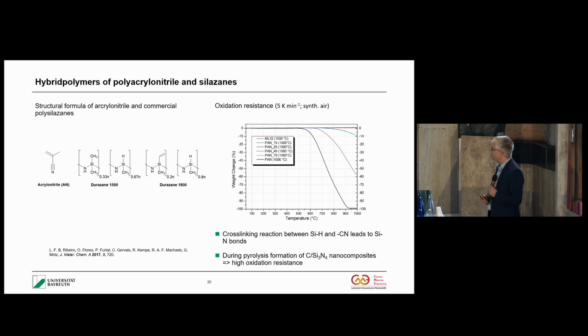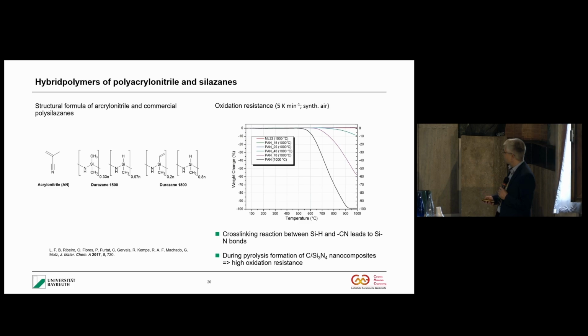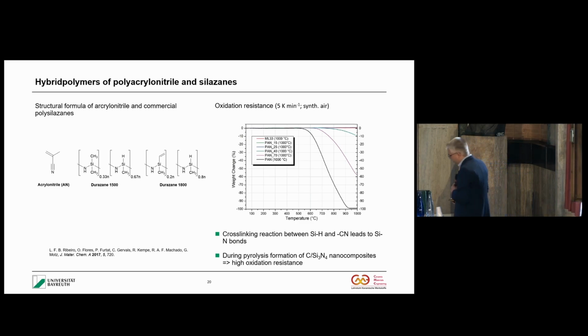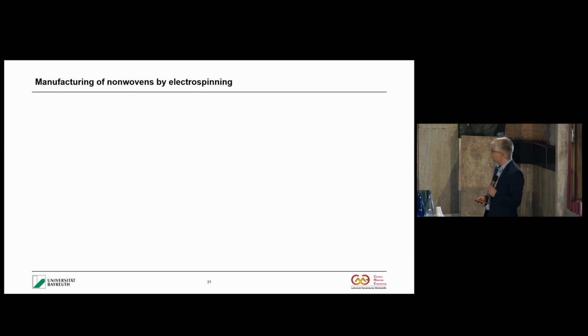with a group from Brazil, showing that the oxidation of this is a function of the amount of the polysilazane addition. And there's actually a cross-linking reaction also with the silicon hydrogen bonds and the cyanide bonds leading to silicon nitride bonds. So that means we have a copolymer forming, and that's actually also then improving other properties later, as I will show.